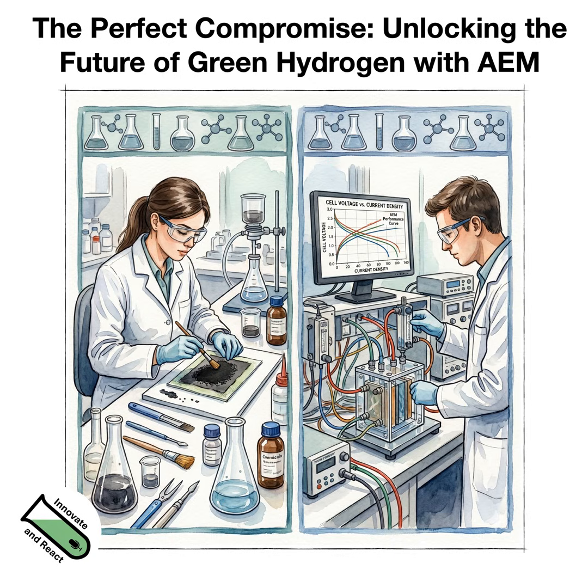Yeah, exactly. Especially because of the ionomer. This is another challenge in the AEM electrolysis. The adhesion of the AEM ionomer is less than the PEM ionomer. The adhesion to what? The adhesion to the catalyst and the catalyst layer. Yeah, okay. So basically the ion conducting part of the membrane is also part of the dispersion that we spray coat. Then you have this system of catalyst materials and conducting ionomer. These ionomers act a little bit as a binder and glue your catalyst onto your PTL, for example, or onto your membrane.